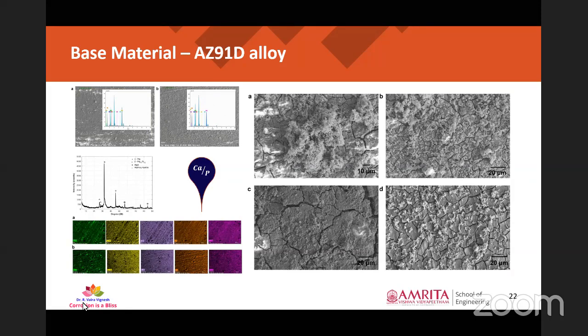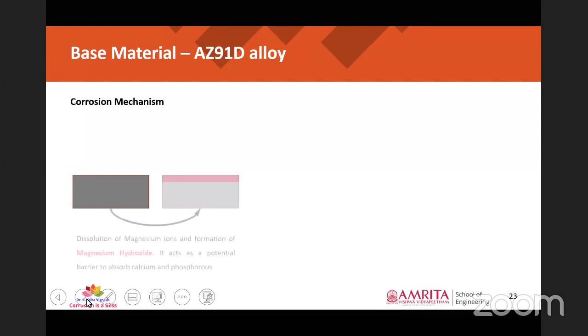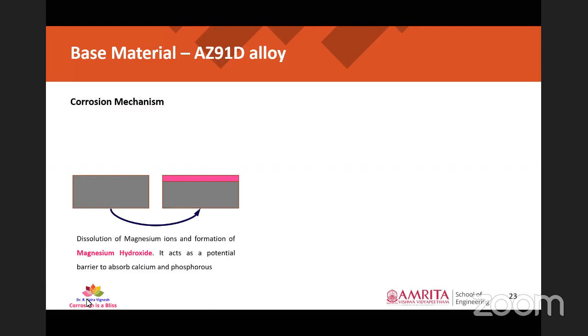So this is one of the things that made us go towards improving the corrosion resistance of this AZ91 alloy through some reinforcements. Breaking down the corrosion mechanism, it is given over here. Once the material is immersed in normal human body solutions, it will develop a layer of magnesium oxide. And this magnesium oxide will be converted into magnesium hydroxide, because it is present in an aqueous solution. So the dissolution of magnesium ions and formation of magnesium hydroxide takes place, and this magnesium hydroxide is a very active compound.